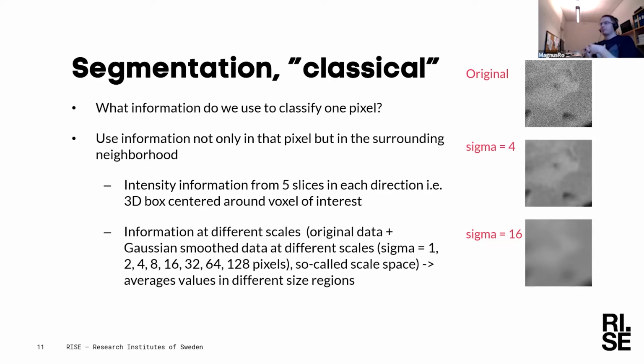And then we extract information at different scales by basically a Gaussian scale space, where we smooth the data with a Gaussian with different standard deviations, corresponding to different spatial scales. And you see some examples of what the data might look like here. And then we take this data, which is for a bunch of different scales, for a bunch of different 2D slices, and we plug it all into a random forest classifier.